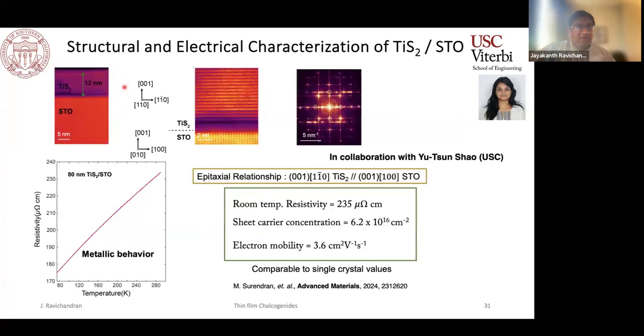The last one in the binary category is this titanium disulfide. We were able to grow fairly textured materials. Their in-plane coherent domains are not necessarily as large as what you would see in some of the CVD techniques people use, where they get these large triangles, but we are trying to grow them uniformly everywhere, and we don't really limit our flux control as much as what you would do in the case of CVD in the high pressure turbulent regime. But nevertheless, we can get fairly textured films, good metallicity with a very large RRR, comparable to single crystal values in the literature, suggesting that the films of this quality are fairly good.